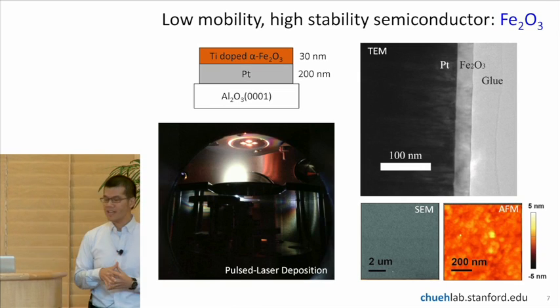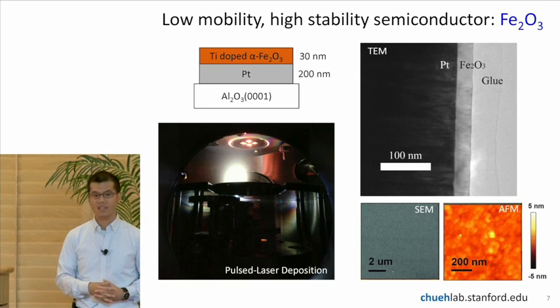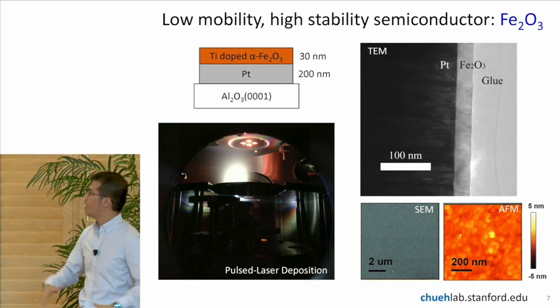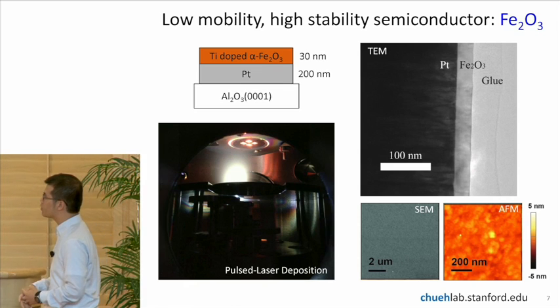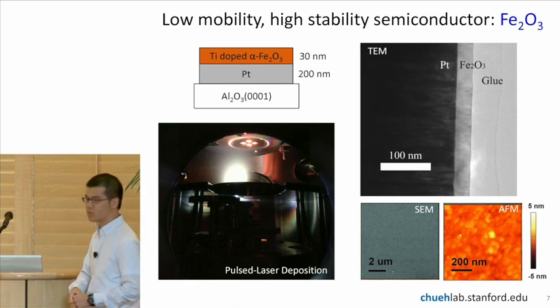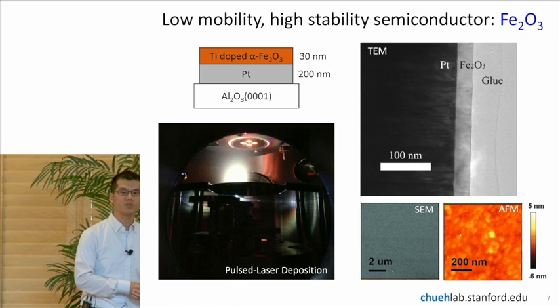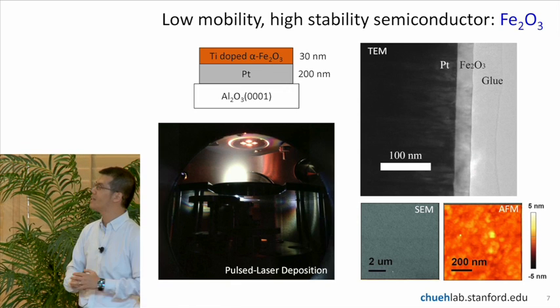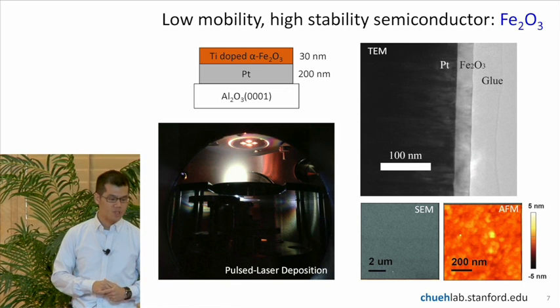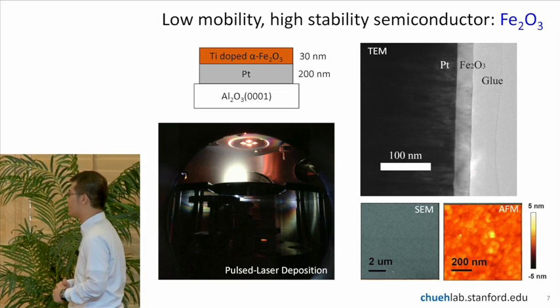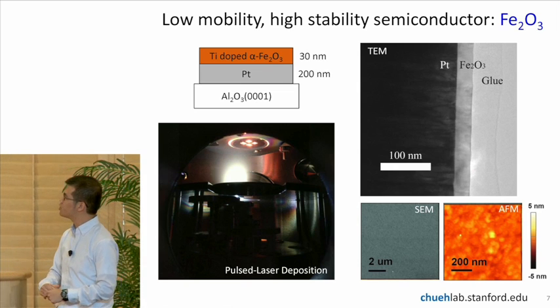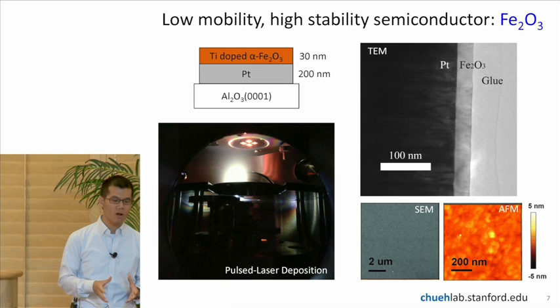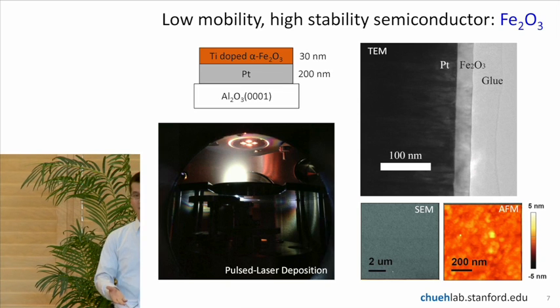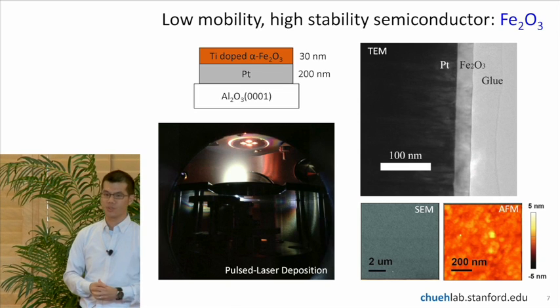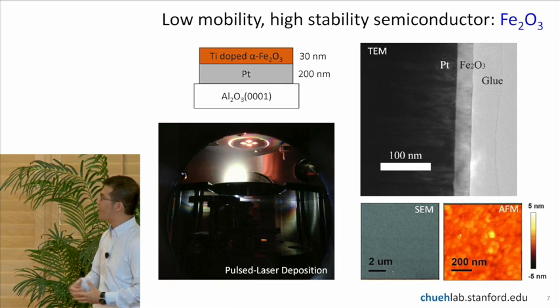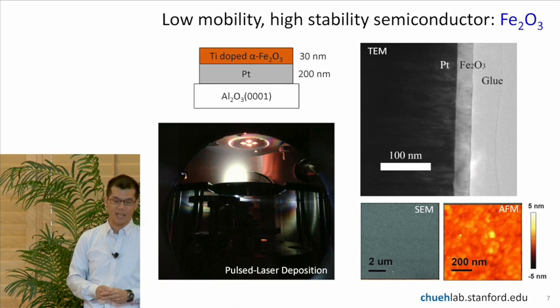So we first examined this iron oxide in a thin film geometry. In my group, we do a lot of fundamental research with model systems. So we use pulsed laser deposition to make a very thin 30 nanometer film of iron oxide on a platinized sapphire substrate. And you can see we were able to make a very, very high quality structure. This is a little bit in contrast with the nanostructure that you see with PECs, but this allows us to control the morphology perfectly.